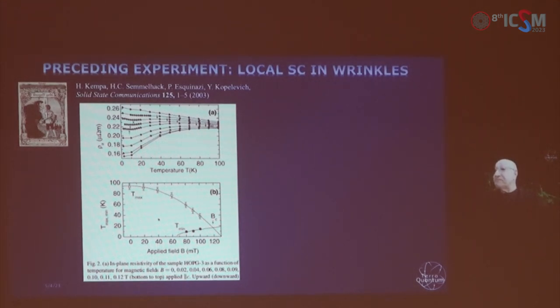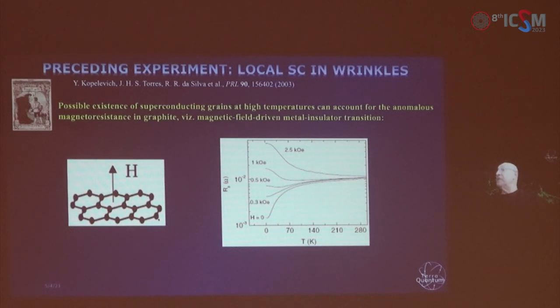If we change, for example, the magnetic field, we can see that this local superconductivity of graphite disappears, and basically what one observes is the transition from this local superconductivity to the insulator. This is the repetition of a similar experiment in terms of the resistance. The fact that the resistance is not going to zero, even in the absence of the magnetic field, indicates that this superconductivity is local and that the contribution of the normal phase is noticeable.